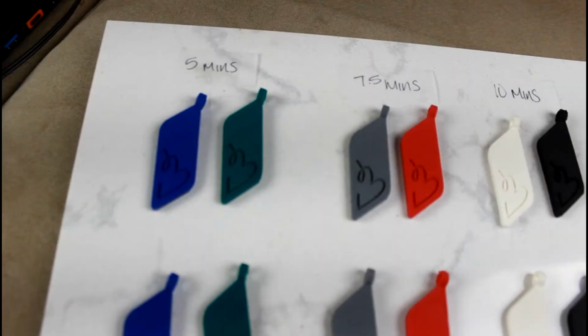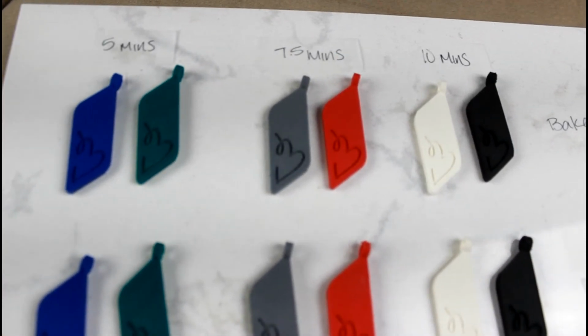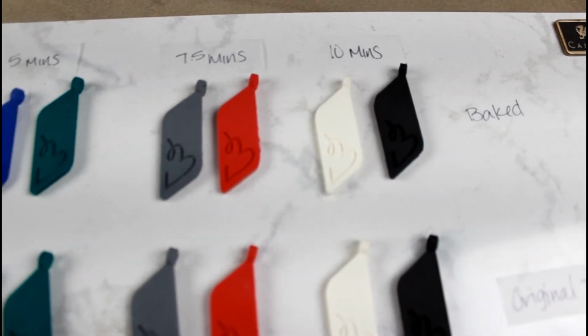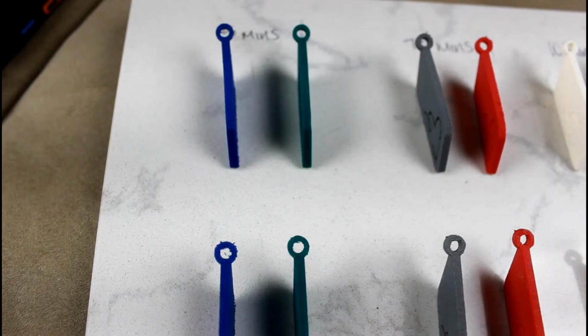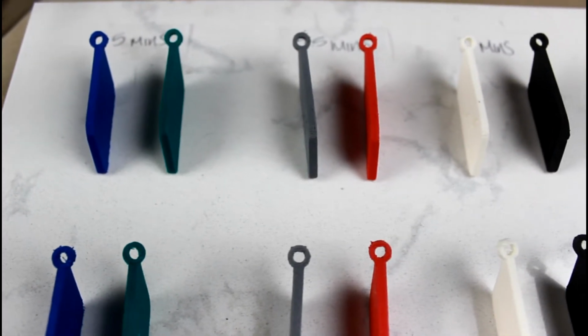Now these are really small keychains, so I decided to bake them for 5 minutes, 7.5 minutes, and 10 minutes to see how that affected the print. At 5 minutes, they turned out great. At 7 minutes, they turned out pretty good. There was a tiny bit of warping on one of the pieces. At 10 minutes, both pieces warped.